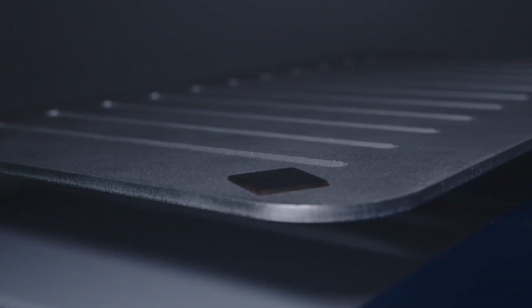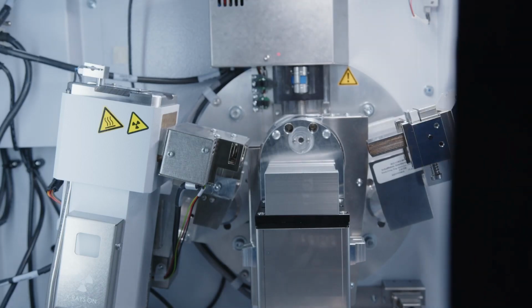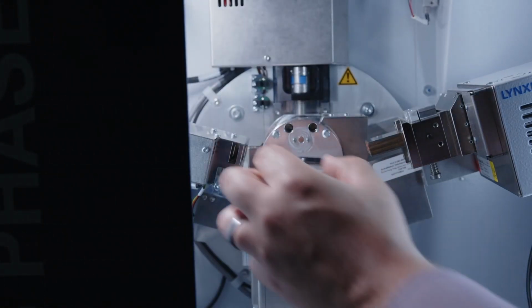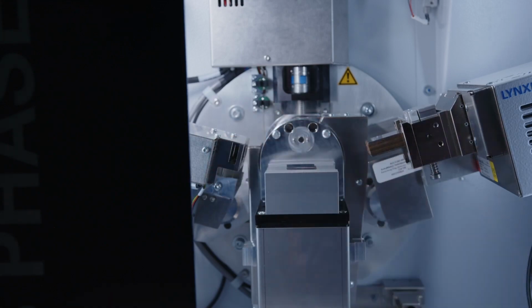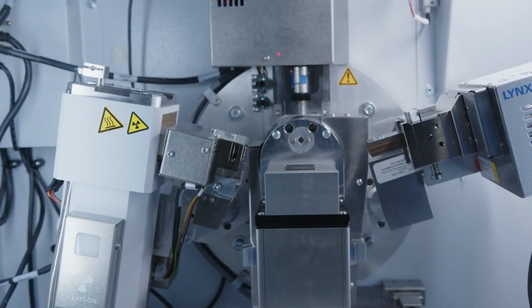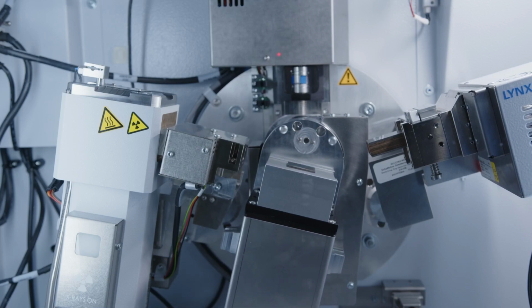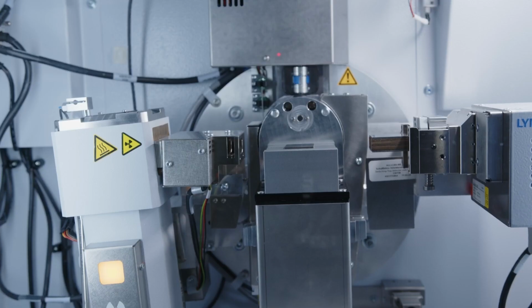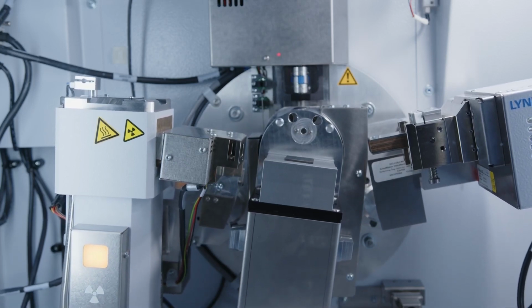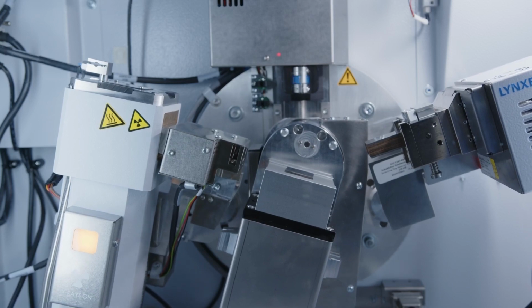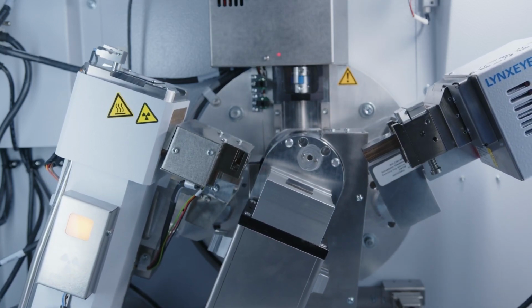Thin films, sometimes referred to as coatings, allow engineers to change the properties of the surface of the material. These coatings can be used to modify the surface finish, add protection, or bring electrical and magnetic properties to the component. Oftentimes, measurements are carried out with a low or grazing angle of incidence to reduce the penetration of the X-ray beam into the underlying substrate. Grazing incidence diffraction, also called GID, is most commonly used for phase identification, but can also be used for depth-controlled residual stress analysis using the multi-HKL stress method.